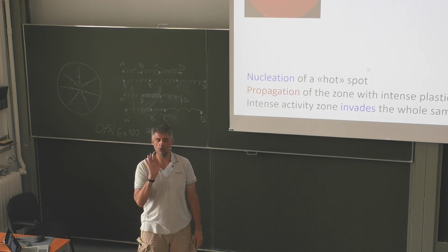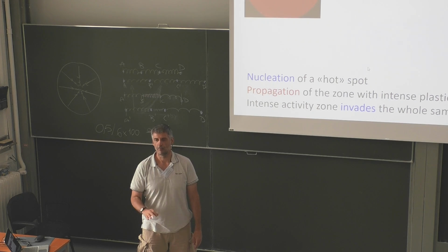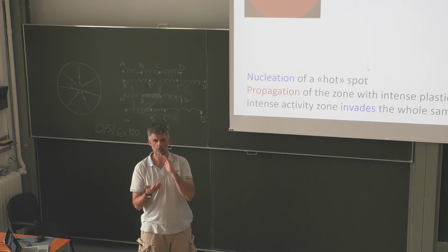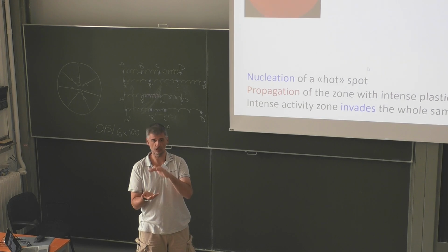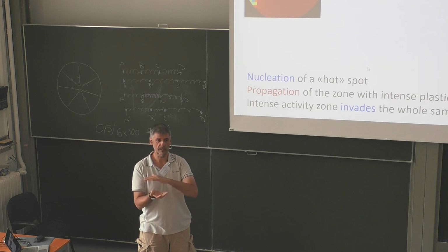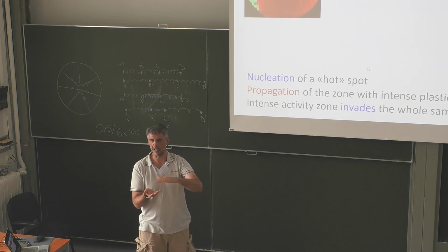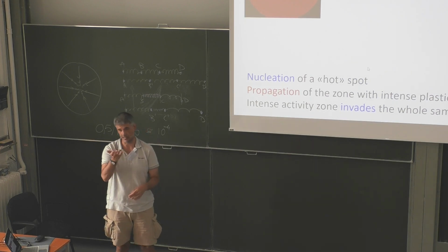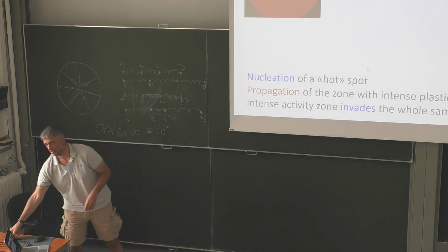Slip. What we do know is that post-mortem, when we open the rheometer, we observe that the gel sticks to both plates. So this is not slip from one plate or whatever. It is really some kind of fracture and failure that has occurred in the bulk. You have to play chemical tricks to make sure that your agarose gel really sticks to the plates. Otherwise, yes, slip would be what you observe.